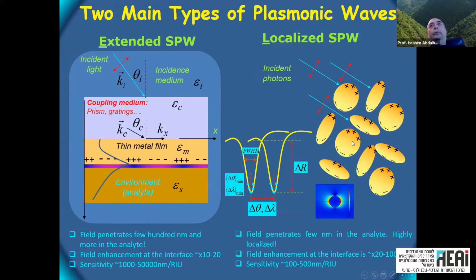it's usually a random medium. It does not make sense to measure it as a function of angle. We measure it as a function of wavelength and look for what's called the minimum in the reflectivity or transmission, or 1 minus reflectivity minus transmission, which is kind of the absorption plus scattering effects. We see a minimum, and this minimum is again sensitive to the refractive index of the medium.